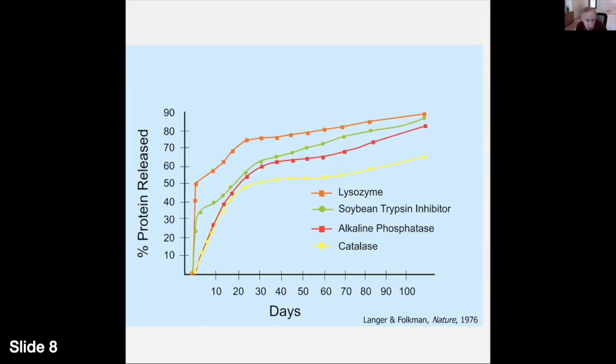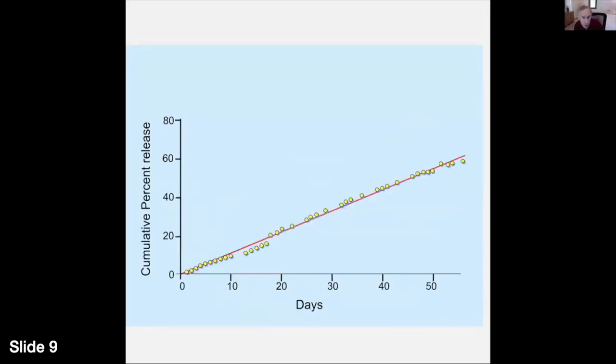For me, I didn't read the literature. So I kept trying. I actually still found over 200 ways to get this to not work. But eventually I was able to make little microparticles or nanoparticles. And we published in Nature in 1976 that you could use this approach to really release molecules of any size. These are proteins, but we also did peptides, nucleic acids, polysaccharides, and so forth. The next slide shows a demonstration from a paper we wrote that you could get constant release.